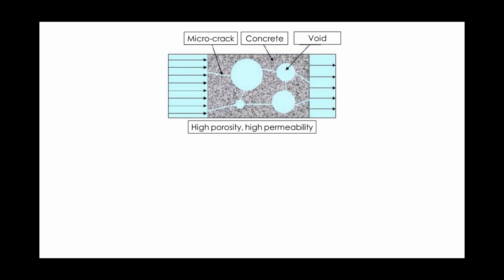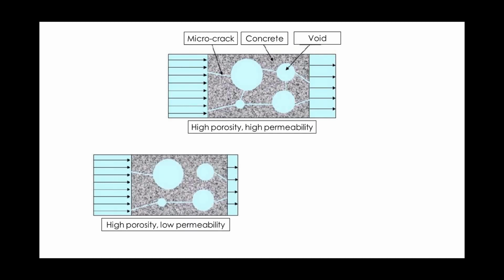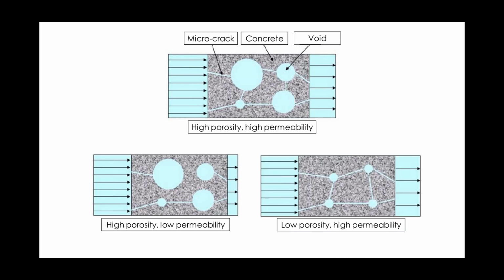So as you can see in the photo, we have microcracks, we have voids inside the concrete, and all those voids are connected, so I can tell this is highly porous and highly permeable. But in other words, if we have high porosity, but these pores are not internally connected, we may have lower permeability, which is kind of an advantage as it's going to increase the durability of our material, which is concrete. Also, if we have low porosity and the pore size is small, it doesn't mean we don't have a permeable concrete, because all these pores can be connected to each other.